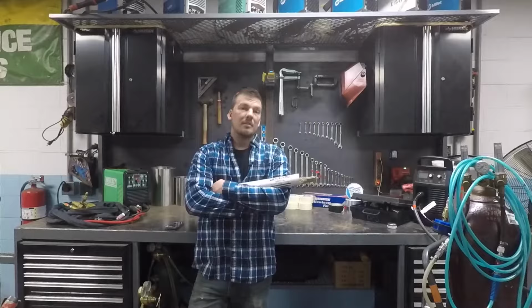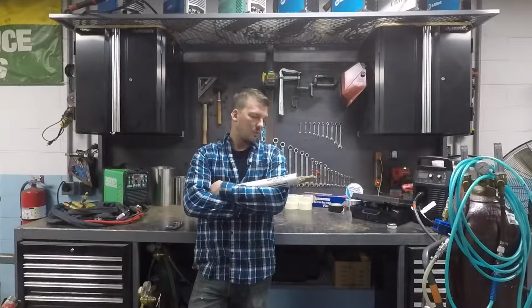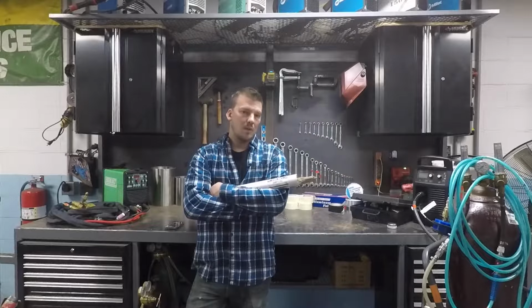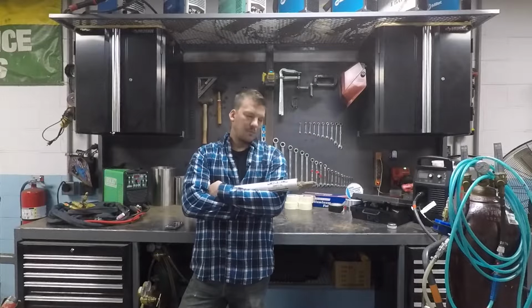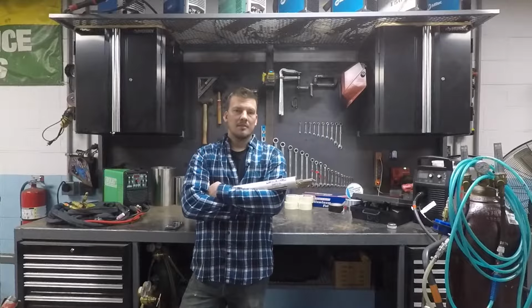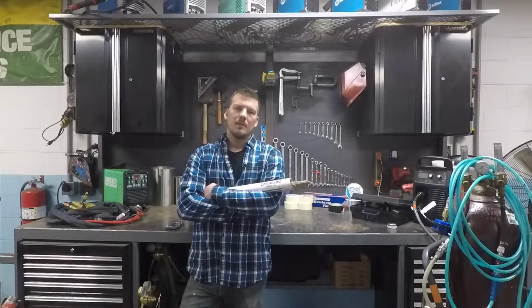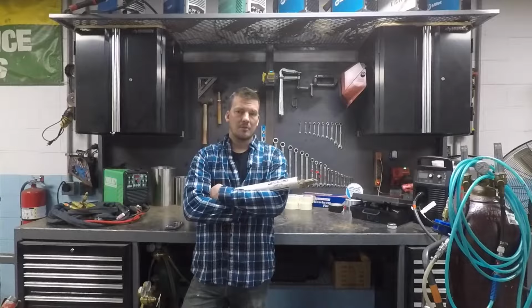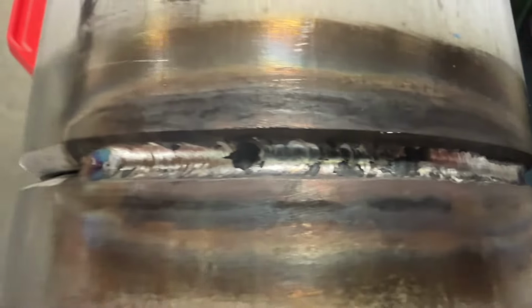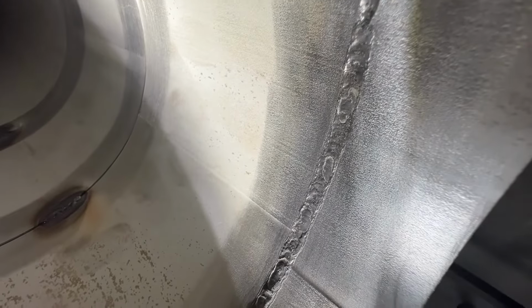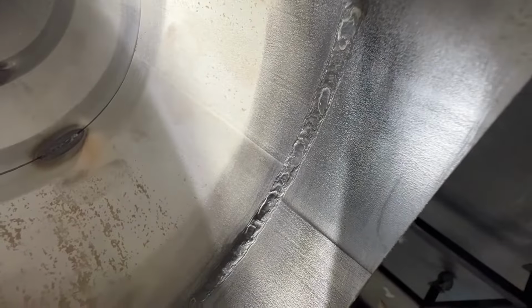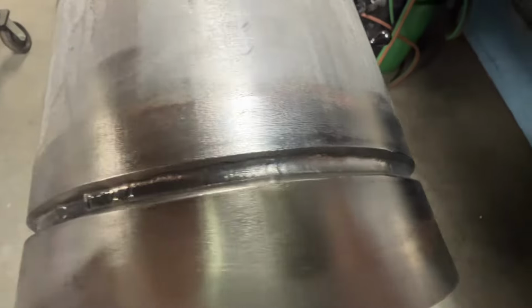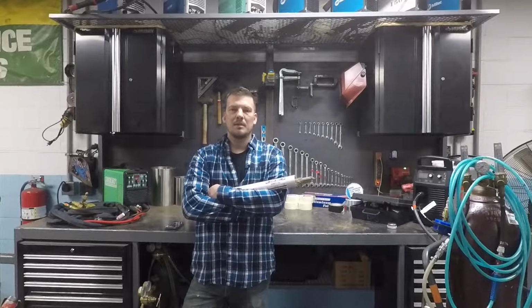It's worth mentioning that there are flux-covered stainless filler wires for welding stainless without a back purge. These can also be known as mud rods or dirty rods. This brand is Cormet. It is challenging to weld with because of how dirty that flux-filled puddle is, not to mention it leaves a slag inside the pipe that you can't get out unless you can reach it. Not ideal for every situation, but for applications like large stainless vent piping, flux-coated TIG wire can be a time saver and argon saver.